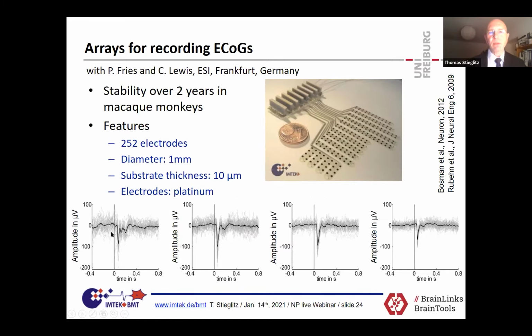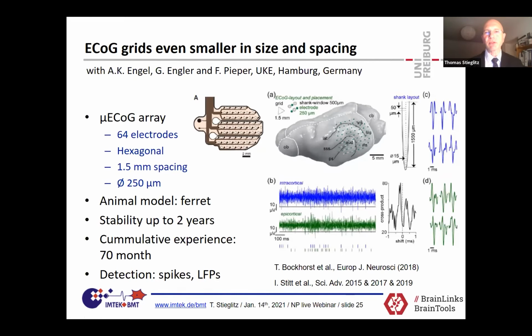And we've seen that we got a quite good signal to noise ratio even after 6 months, which is here on the very right-hand side, having platinum electrodes, only a substrate thickness of 10 micrometers, and relatively large electrodes on that. Assembly was the hardest part, to be honest, to solder and glue all those connectors to the array. That was very promising. And we got approached by other colleagues from Hamburg and made it smaller, and they went into ferrets, where not so many groups worldwide are working. And the arrays were also stable there.